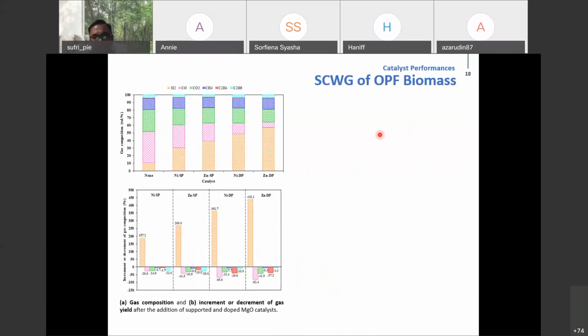All the synthesized catalysts in this research were used to catalyze the supercritical water gasification of OPF biomass into syngas. Remember, syngas is a mixture of gases, but we try our best to increase the yield of hydrogen in the syngas. Without catalyst, the OPF biomass can also be decomposed in supercritical water, even at the low gasification temperature.